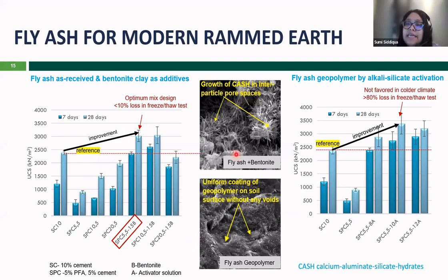And we also see the other way to look into this example, in terms of the fly ash as geopolymer by alkali silicate activation. And then we saw a similar type of data over here with the reference. We saw the improvement after 28 days. And it's not favored in the colder climate because we saw more than 80% loss in the freeze-thaw cycle.